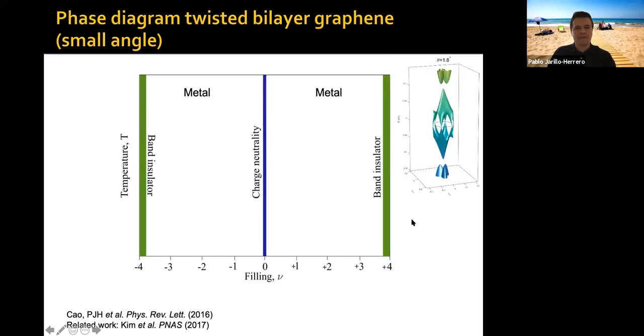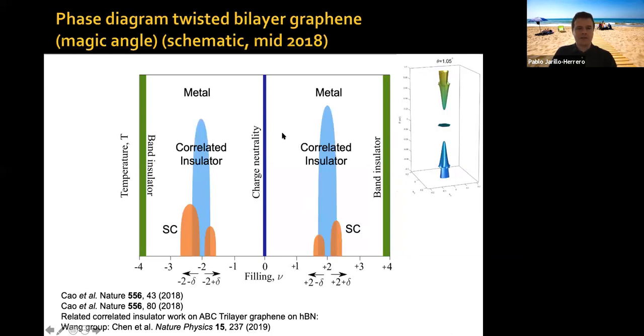Now, what happens if we have small angle twisted bilayer graphene, but not yet magic angle? Well, then as you see here, you have band gaps that develop here. And now I'm changing from density to filling factor, which is a notation that many of the other speakers have used already in the school. This filling factor tells you whether you put one, two, three, or four electrons, or one, two, three, four holes per moire unit cell. And you see when you put four electrons or four holes per moire unit cell, you reach these band gaps. So you have a band insulator. This is something that we saw already a number of years ago in small angle twisted bilayer graphene, has been reproduced by others, and it's interesting behavior, but you can more or less understand it in a single particle picture.